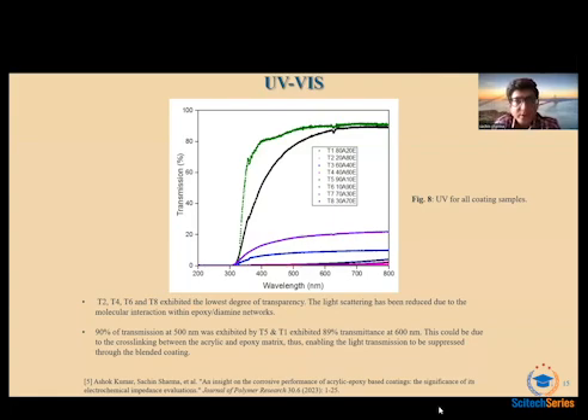So we can see that T2, T4, T6, and T8 contained lower content of acrylic, at the same time having higher content of epoxy, right? So that was important. So 90% of the transmission was exhibited by the T1 and T5 samples, at approximately 89% at 600 nanometers. However, at 500 nanometers, it exhibited approximately 90%. So this was mainly due to the cross-linking that occurred between the polymer matrix, and therefore this enabled the light transmission to be suppressed through the blended coatings.